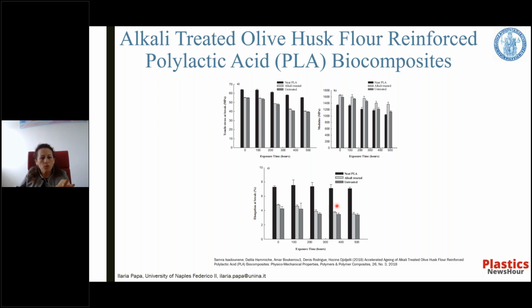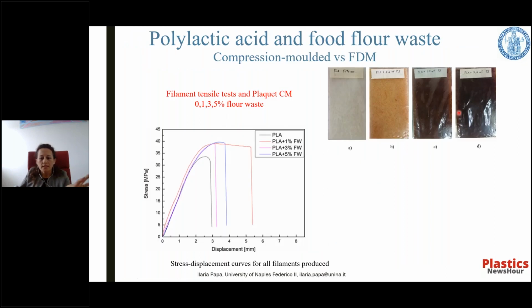That said, we want to show also my contribution, the contribution of my group in the slides, that is focused on the formulation based on a commercial polylactic acid resin modified by the inclusion of food flour waste up to 5% by weight, and compares the performance of the samples obtained with the conventional technology, compression molding, with those made using 3D printing, with the aim of enhancing the benefits of one process over the other. We have printed and also obtained by compression molding specimens from the different base formulations indicated in this slide, and they were experimentally compared by thermal, mechanical, and morphological analysis.